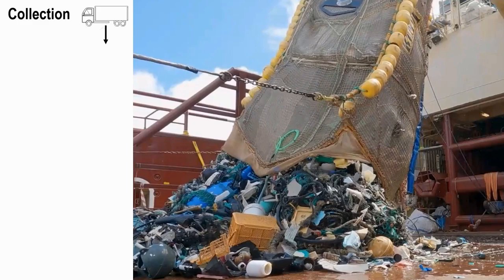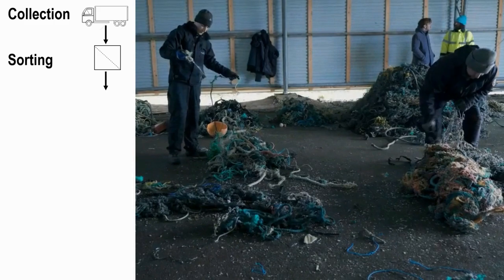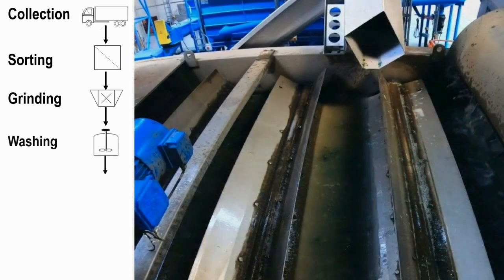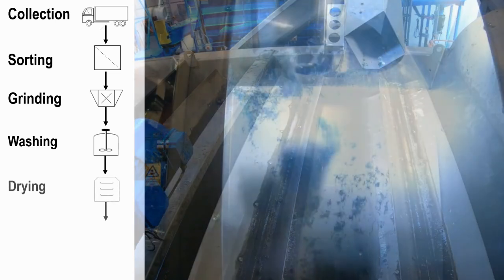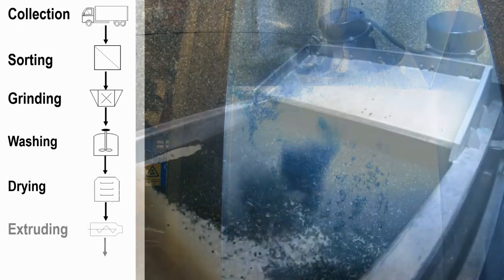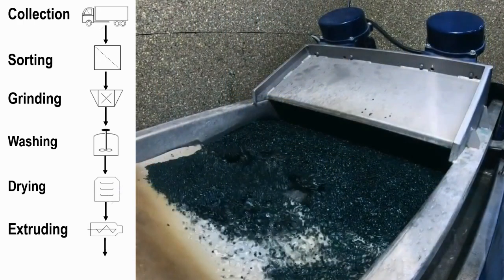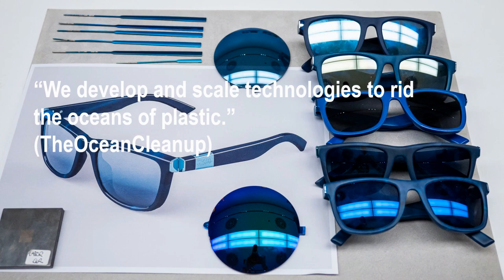Then they sort it, they grind it, they wash the ground material. They dry it afterwards, and they extrude to have granules, or pellets, as others would call them. And here we are. In the end, you can make a new product out of these granules, and in this case, sunglasses. The Ocean Cleanup says we develop and scale technologies to rid the oceans of plastic. This is their mission.